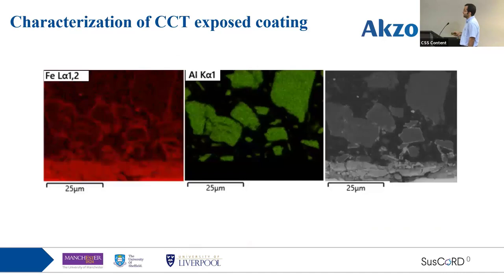Another interesting image is that when we looked at the particles near the corrosion sites, there is a cluster of particles. We could see corrosion product at the interface of almost all of them. So it is possible that these particles are providing the transport path, and these interconnected particles and the interface of them is a weak point. When I say a weak point, we still need to do more work because we have not clarified whether a detachment has happened or whether there is some change in the chemistry there that makes it more hydrophilic and allows more transport of different ions through it.